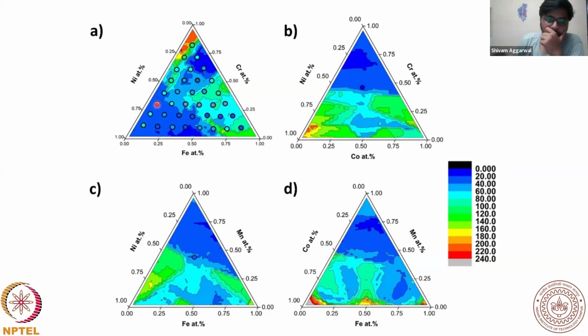So they plotted this and got the value according to that. And you can select your region from this plot. So where you have to work, like if you want a stacking fault energy around 60, and if I talk about nickel, manganese, iron, there is this region and this region where I can get that stacking fault energy. So I can choose that. In this way we can accelerate our metal discovery with targeted properties.